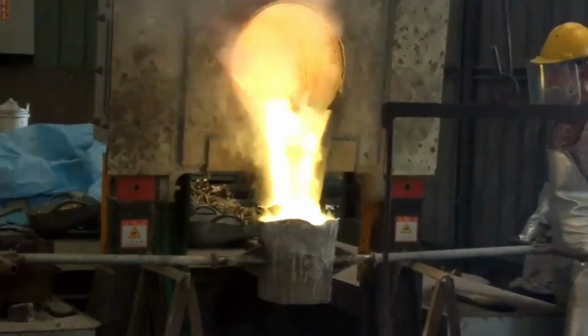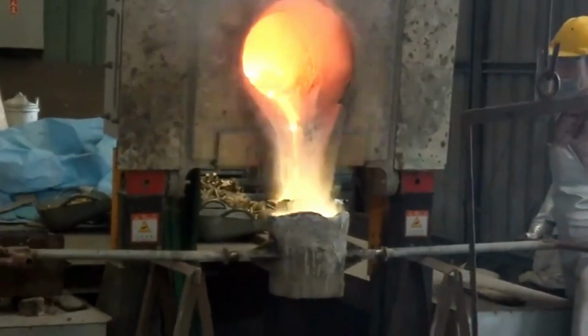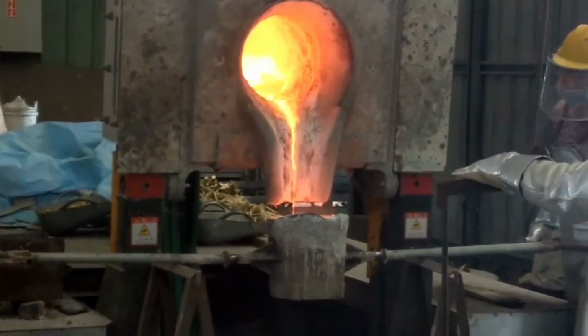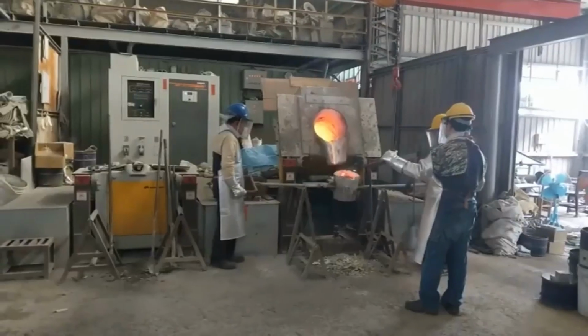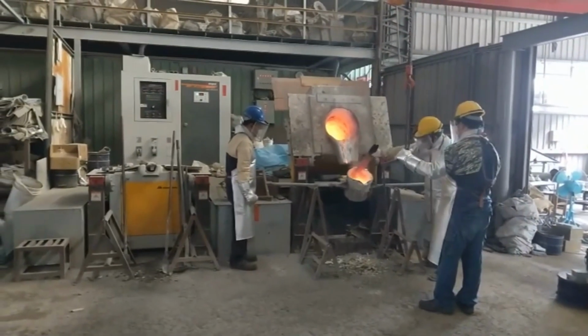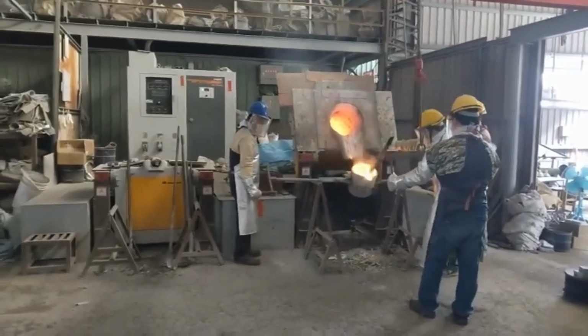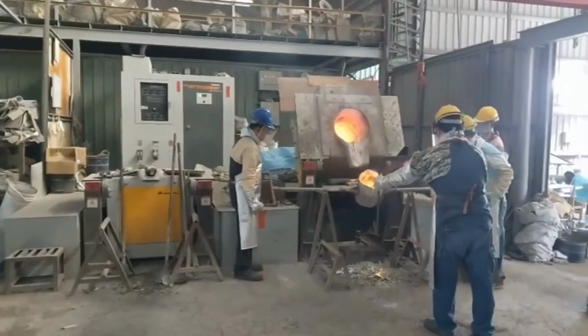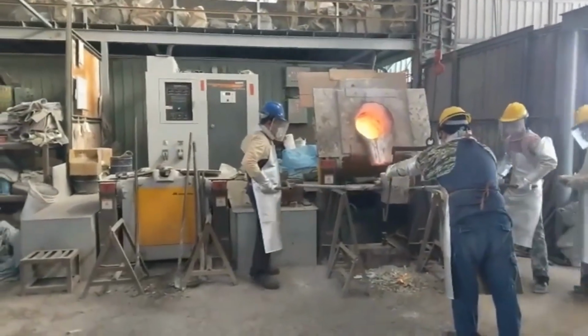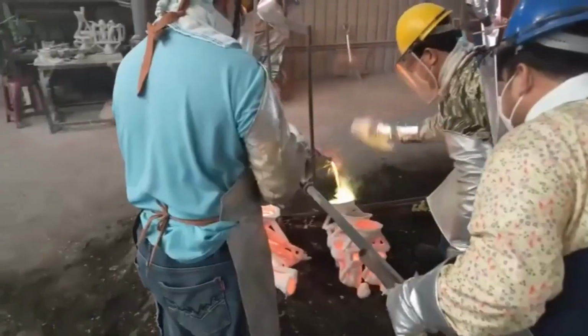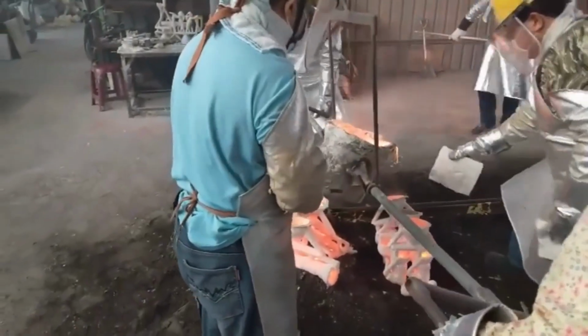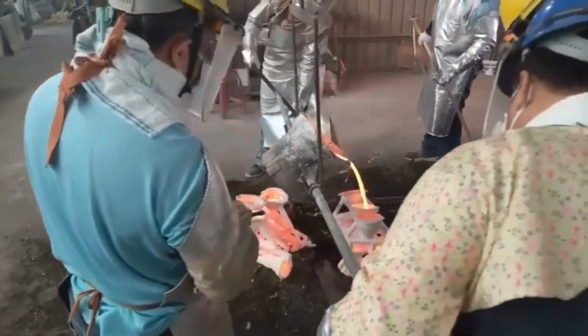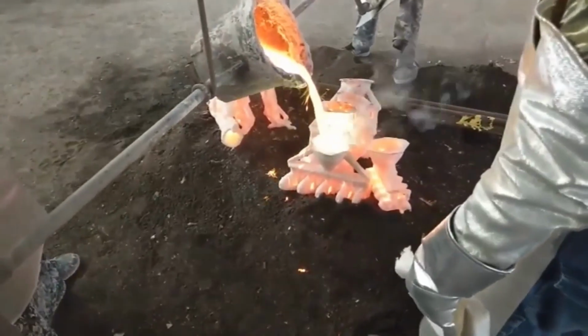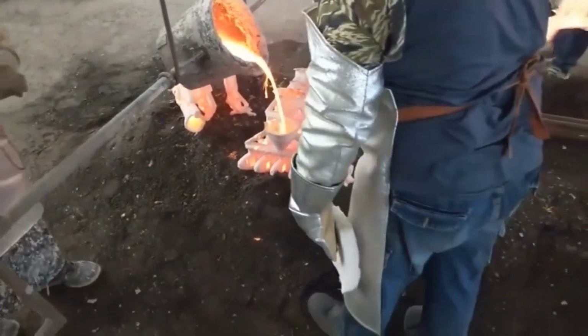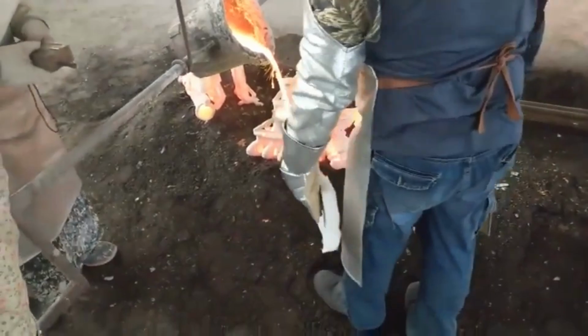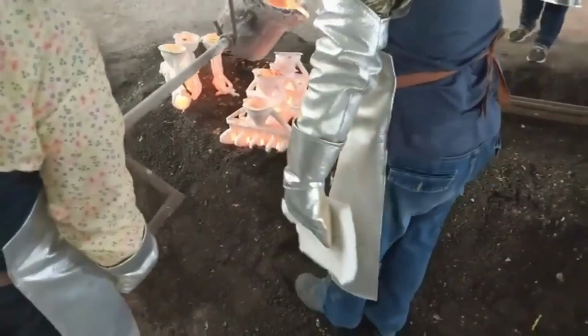Next comes the critical step of creating a ceramic shell around the wax assembly. The wax tree is dipped into a slurry made of colloidal silica mixed with fine refractory powders such as zircon. Excess slurry is drained, and the assembly is coated with layers of fine and coarse sand. This dipping and coating process is repeated multiple times to build a robust ceramic shell of the required thickness. Each layer must dry completely before the next is applied, ensuring a shell strong enough to withstand the pressure of molten metal during pouring.